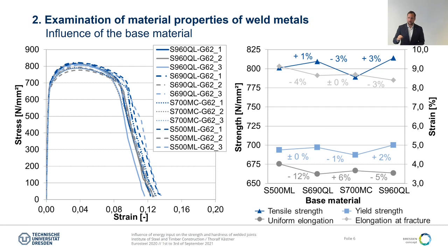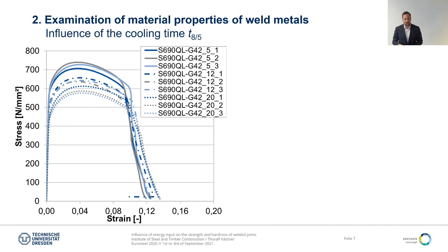We have a scattering within the strength values we expected, and also on the elongation we have a large reduction in the elongation at fracture, but having a look at the total values, this reduction is also negligible. So by using this specific test specimen, we could find out that there is no specific influence of the base material on the strength of the weld metal. But what we can see is that there is a huge impact of the cooling time T85 on the mechanical properties.